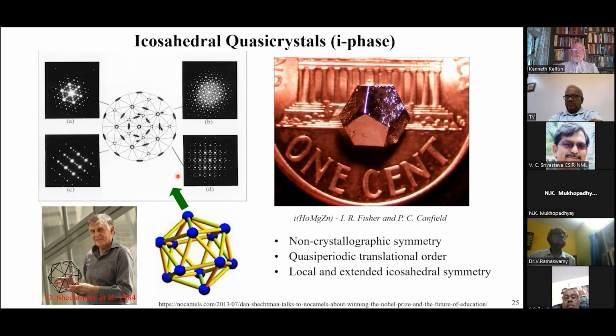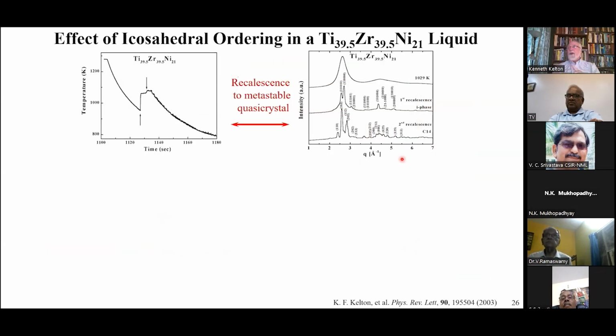It's often thought that these quasicrystals are disordered high-temperature materials, but this is one that was grown by Fisher and Canfield, a quasicrystal to macroscopic size, and you can see it's a beautiful dodecahedron. If you looked at the scattering from this particular sample with synchrotron X-ray scattering, you would find that this has higher quality than the single crystal silicon they use for monochromators. So it's not a disordered structure. It's an extremely ordered structure. But I need to use this because I want to combine those two slides I showed you to look at a titanium zirconium nickel liquid.